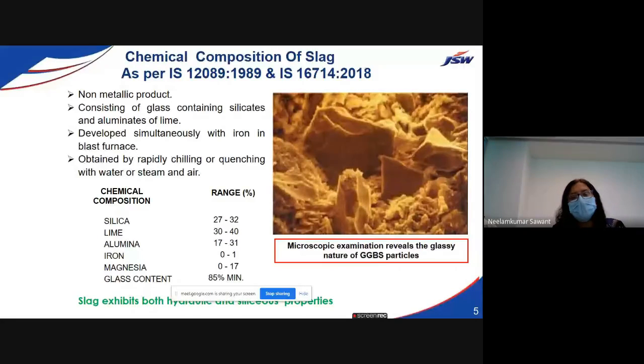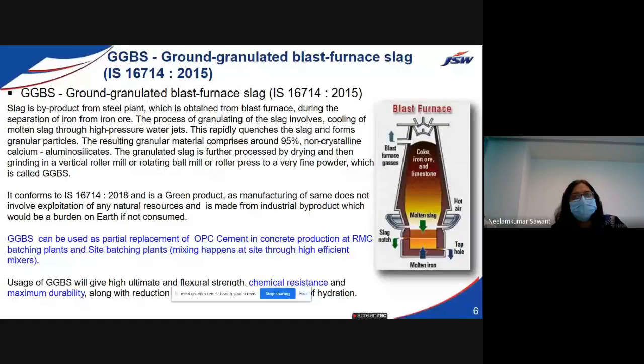Along with that are alumina, iron, magnesia, and the glass content is 85% minimum. The JSW slag GGBS glass content is between 90 to 97.5%. So you can see the microscopic examination of the glassy nature of GGBS particle. Highly reactive, highly siliceous, and also having very good amount of calcium oxide.